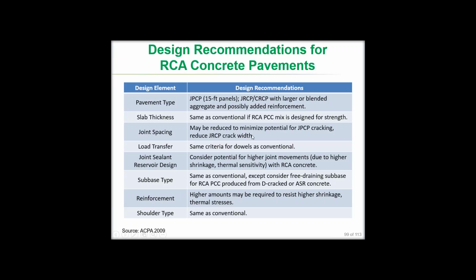Joint spacing might be reduced, as I mentioned previously, for both jointed plain and jointed reinforced. Load transfer is the same. Same criteria for dowel bars being used. Joint sealant reservoir designs, if you're a state that does do joint sealing, consider the fact that there may be more shrinkage taking place because of the higher mortar content, so there may be a little bit more movement at those joints. You may need to have a little wider joint sealant reservoir to accommodate that movement.